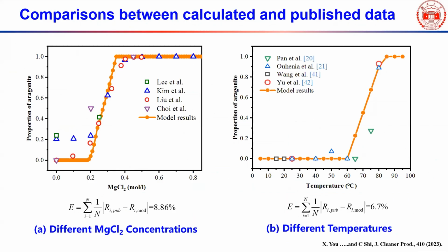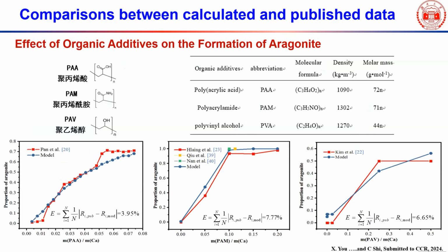Well, this is a comparison between our model and the published data, and you can see that for magnesium chloride concentration, our model fits the experimental results very well. And also for temperature, you can see that from 60 to 80 degrees C, aragonite starts to form, and when it's over 90 degrees C, you will mainly get aragonite instead of calcite. And when we use different organic additives such as PAA, PAM, and PVA, you can see our model also fits the experimental results very well here.